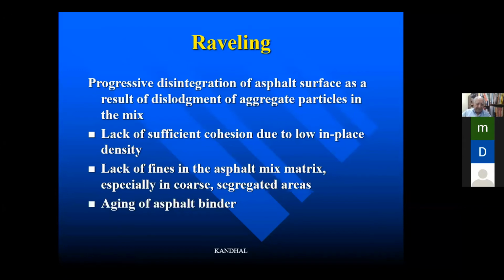Now, I've seen raveling in the US, I've seen raveling in India. If I build a bituminous road and within 1 year, I start to see raveling, which is loss of the surface, first, I see the fines are coming out and then bigger particles are coming out. Within 1 year, it happens, you can bet that 90% of the time it is because of the low in-place density. I did not compact the mix well at the time of construction. So you take a core and you check the density, you'll find out 90% of the time, you will find the lower density, which caused the raveling problem.